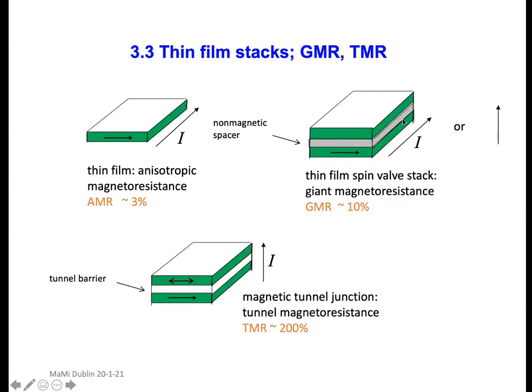If we replace the copper by an insulator and we turn the current direction from in plane to perpendicular, then we have a tunnel barrier where we can get, in fact, 200% of magnetoresistance. These are very, very, very important developments. And in fact, Grünberg and Fert were given the Nobel Prize for not only observing it, but also explaining it.